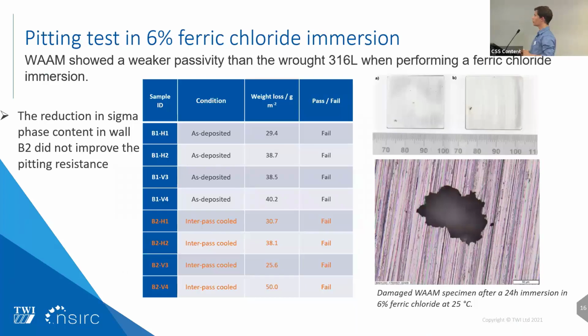We've also performed pitting tests in 6% ferric chloride. That was 24 hours immersion at 25 degrees Celsius.